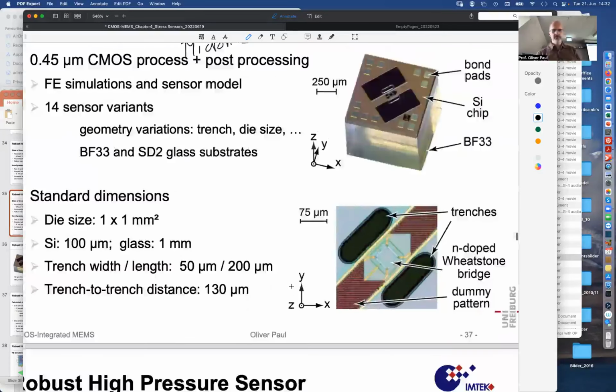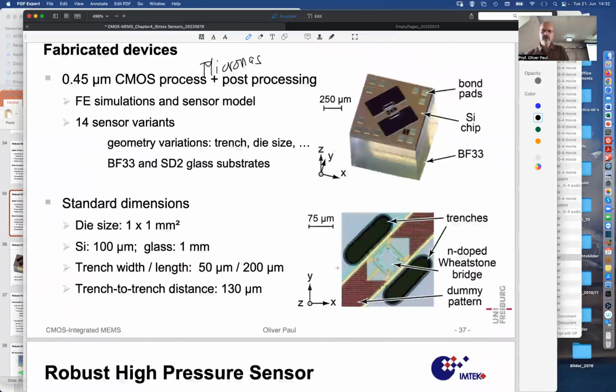Yeah. And so you see these trenches. These trenches are produced with standard micromachining techniques. Silicon etching techniques. You know how to do that. You put the thing into a deep reactive ion etcher with a mask that is thick enough to protect the surface of the CMOS structures against 100 micron deep etch into silicon, a vertical etch. And this is this trench that goes down. And this trench going down then creates a silicon wall here on the side that allows this structure to, for instance, contract laterally if pulled longitudinally.